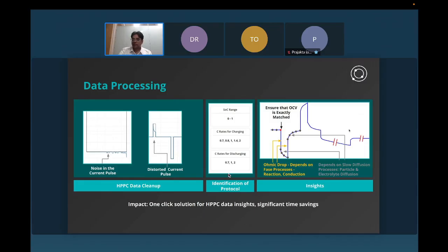Now, then later you have a recovery period. In the recovery period, you have basically set the current to zero. Now there is no chemical reaction happening on the surface of the particles, and the lithium at the surface is now getting diffused inside. And because the diffusion surface concentration changes, that leads to this recovery in the voltage. Now, all of these things depend on the parameters that we are talking about here: the reaction rates, diffusion constants, as well as the lumped resistances.